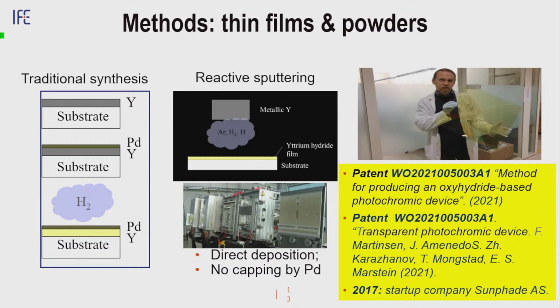But we went a different route. We deposit yttrium in hydrogen atmosphere already, and we get yttrium hydride. Afterwards, we expose it to air, and we get yttrium oxyhydride. This is what we know today. But when we first got this material, it was always confusing why the material became transparent.